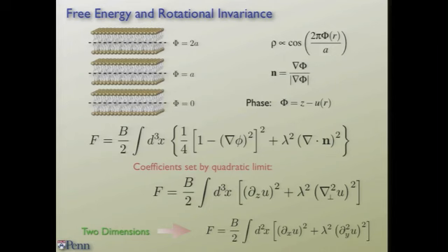So I'm going to say the following thing. Any nonlinear theory that has this as its quadratic limit is a perfectly good explanation of the smectic, because eventually we always truncate at nonlinear order. We have quartic terms, higher order terms in all the strain fields. Whatever theory you write down, I'll write my theory down. Mine will be a nonlinear transformation from yours, but they'll all be nonlinear. But we'll all have to agree on this. In other words, when an experimentalist measures things, experimentalists can always measure B and lambda squared unambiguously. But as soon as they measure non-harmonic terms in the free energy, they have to tell you which free energy they're talking about. Yes, Vincenzo.